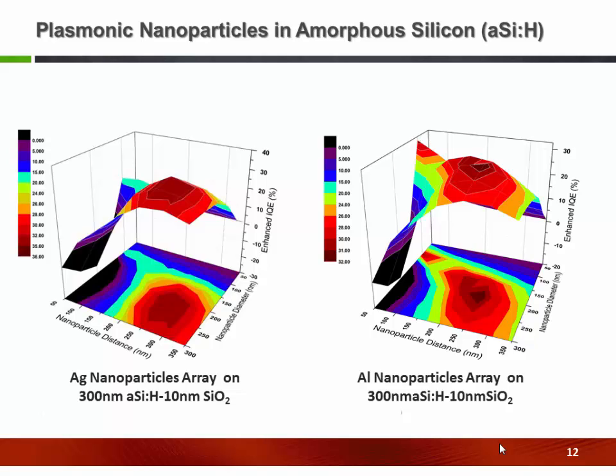I have investigated and seen that for both cases we have an optimal condition with respect to the array parameters regarding the distance and the size of the metal. Both of these show that we could get a high increase in the efficiency. Internal quantum efficiency was enhanced by about 30% for aluminum and about 32% to 35% for silver. Silver shows a better performance compared to aluminum, but aluminum also has advantages as well.